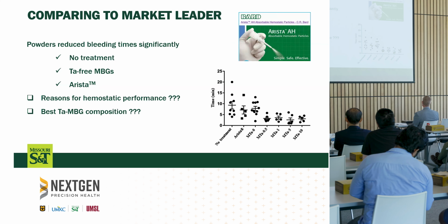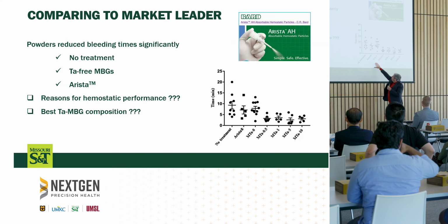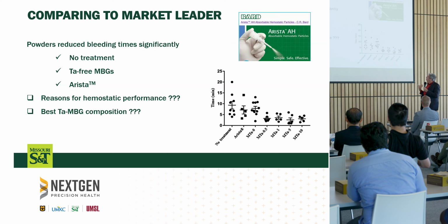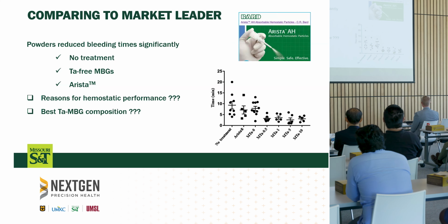When you then look at the next column, which is our tantalum-free version of our Bioglass, we see our material is pretty much about as good as the market leader. But what's really interesting is that when you add tantalum to that material, and then you're using both the chemical and the physical clotting of the material, you see the bleeding time reduces dramatically to about 3 minutes. So it seems from that very rough and ready study that our material without tantalum, just relying on the blood flowing into the pores and causing a clot, is as good as Arista, pretty much. But you add tantalum, it's much better again.